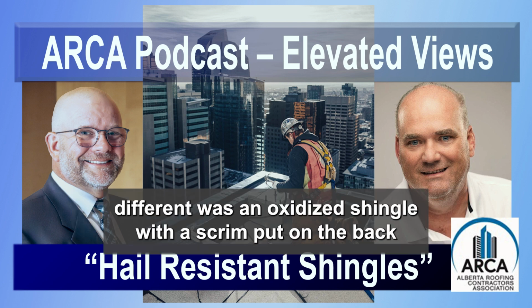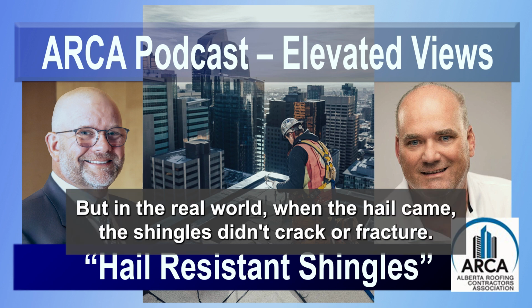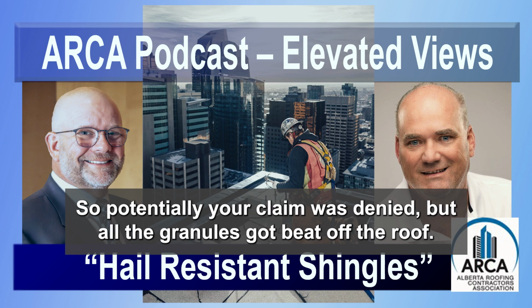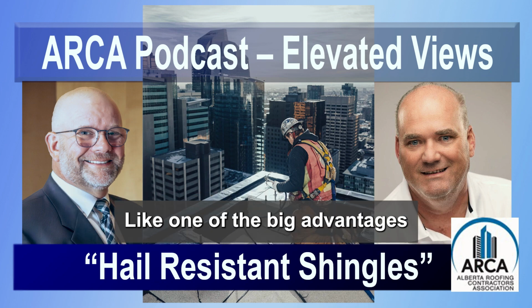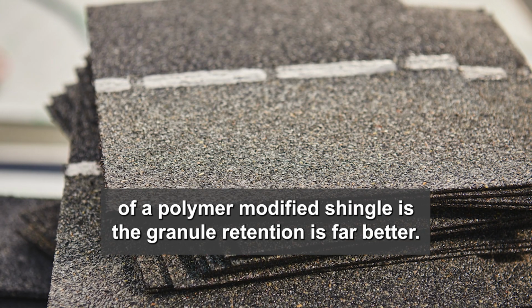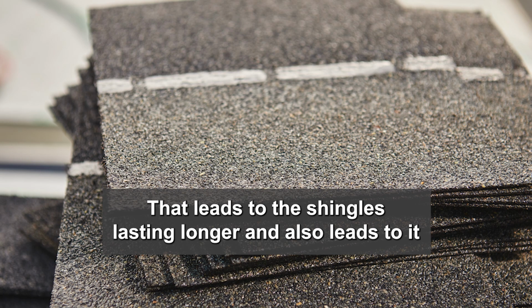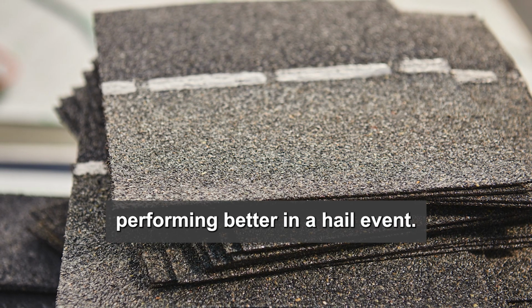There was nothing different. It was an oxidized shingle with a scrim put on the back. That enabled them to pass the class 4 test, but in the real world, when the hail came, the shingles didn't crack or fracture, so potentially your claim was denied, but all the granules got beat off the roof. So back to my earlier point, one of the big advantages of a polymer-modified shingle is the granule retention is far better. That leads to the shingle lasting longer and also performing better in a hail event.